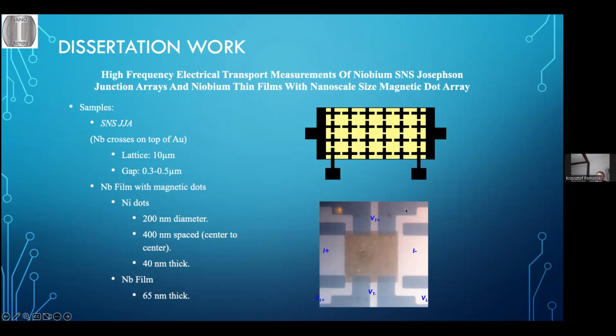But the niobium film has been removed from everywhere except from where the path that makes the circuit. But then this is continuous, and it doesn't show in there, but it's continuously on top of the nickel.